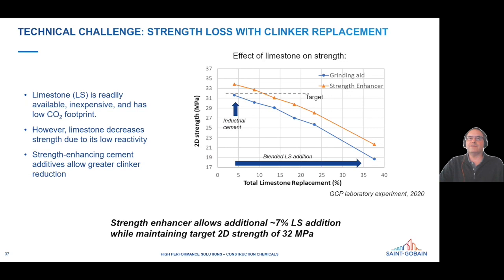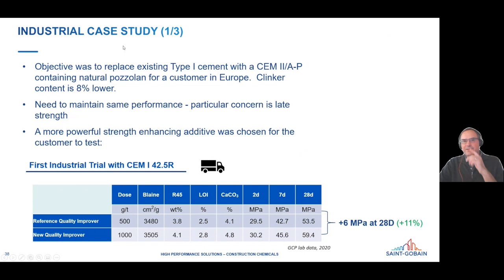And so I just want to show an industrial case study of working with a customer that wants to make cement with a lower CO2 footprint. So in this case, they had the objective of replacing their type 1 cement, which had very little secondary materials and was mostly clinker, with what's called a CEM II/A-P. So that is a pozzolan containing one. This is a natural pozzolan material that's dug out of the ground and then can be added into the cement and does have some cementing ability. So they were going to add about 8% pozzolan, which means 8% lower clinker content, and they wanted to maintain their late strength, which was the problem that they were having.